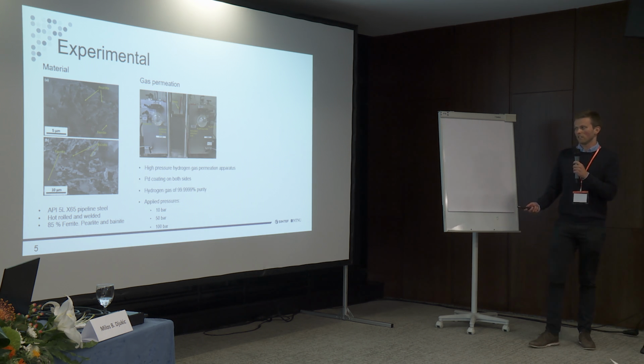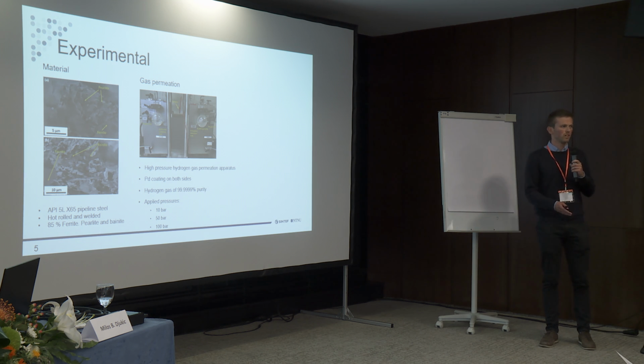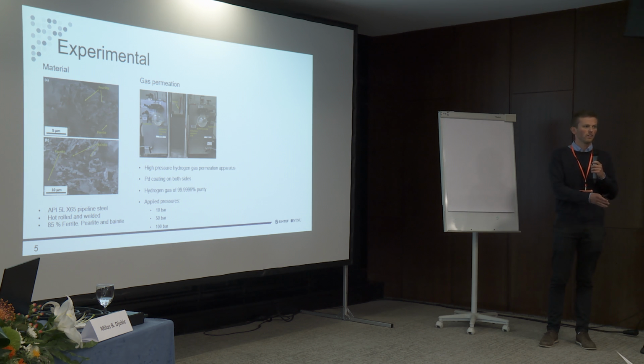It's a high pressure hydrogen gas apparatus where we have a charging autoclave filled with hydrogen gas, and we apply 3 different pressures: 10 bar, 50 bar, and 100 bar. We have our sample here in the form of a plate, coated with palladium on both sides to ensure hydrogen uptake on the charging side and hydrogen oxidation on the detection side. In this chamber, we have 0.1 molar sodium hydroxide solution and apply an anodic potential of 300 millivolts versus the saturated calomel electrode.